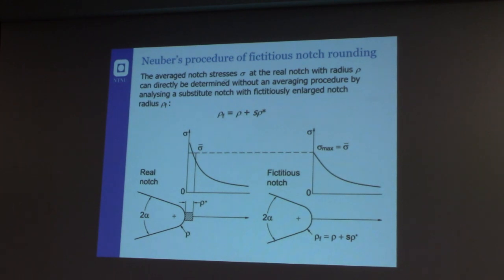In this part of the lecture, I want to introduce some approaches that are useful for design purposes when you are considering notched components. I don't go into much depth, but I want to give you some introduction to this approach. What Neuber first, and after him Radaj, tried to do was to solve the problem of a very sharp notch, a notch with a small notch radius, by averaging the stress close to the notch tip, considering a microstructural support length, which is a material property called rho star.